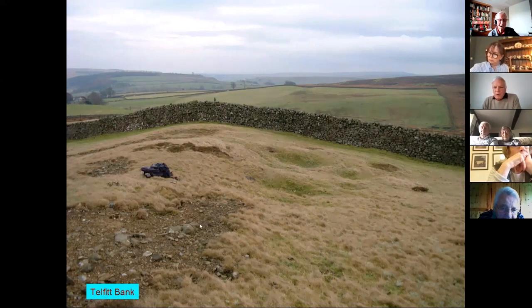And one of the puzzling things we find with many of these is that there are these pits. And we haven't really worked out why there are pits at many of the sites, not just this one, and what they were there for. It's possible that smelting was actually carried out there and people have dug holes to get the last of the lead out. My own company had a smelting works in Bedminster in Bristol. When they took the blast furnaces down, they found tin and lead 15 feet below the furnace. So it's very penetrative, is hot metal. And so that might be one of the reasons.